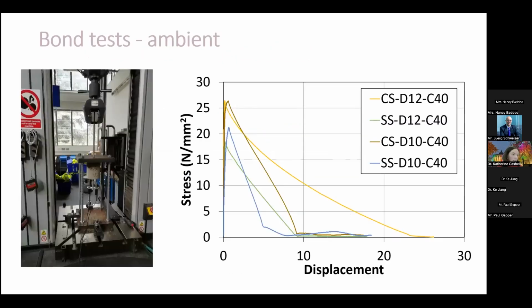Taking a look at the bond, which is so important, of course, for reinforced concrete structures. That composite relationship that develops between the concrete and the rebar. Here we did some pull-out tests, hopefully you can see it over on the left side of the screen, pulling rebars out of concrete and comparing an identical carbon steel and stainless steel sample. Generally what we found is that stainless steel doesn't develop as good bond as carbon steel, but it's not far off. The reasons for that are to do with the rib shape and also potentially the surface condition of the rebars.